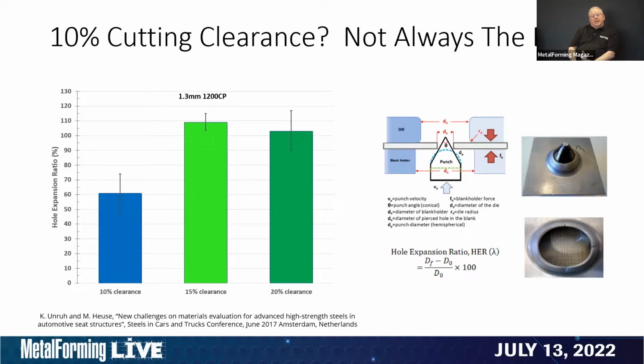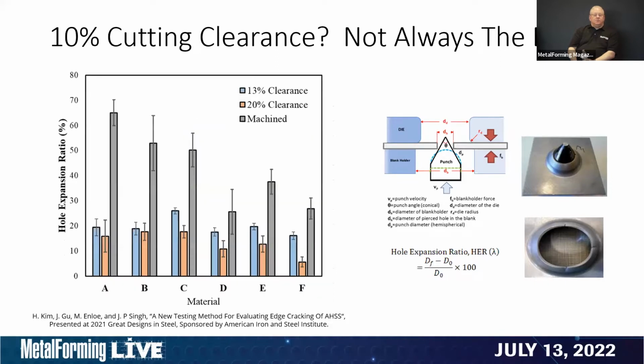And if you're using a 10% cutting clearance, you're going to be able to expand the hole around 60%. But if you increase your cutting clearance to 15%, you almost double the expandability of that hole. So that 10% cutting clearance isn't always optimized for a given advanced high strength steel.